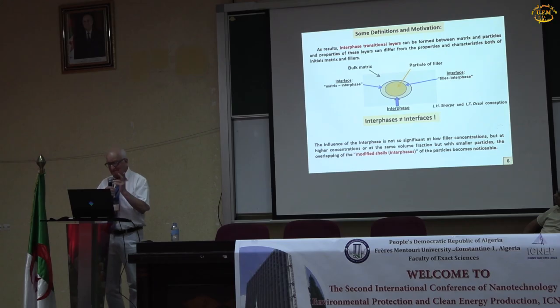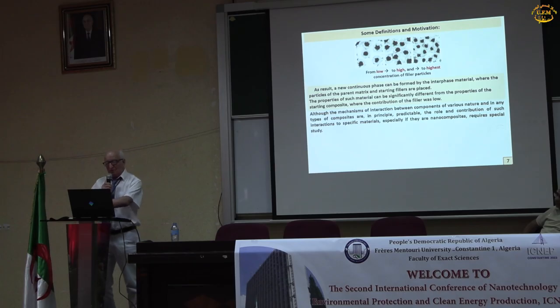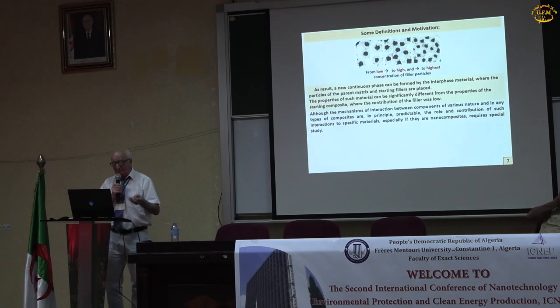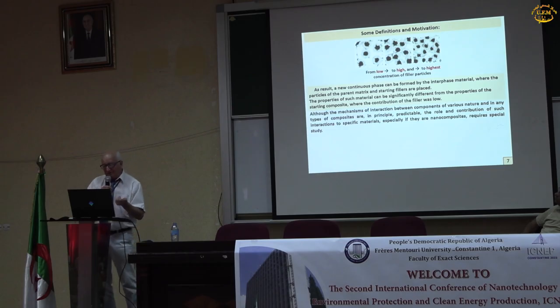It is very important. The influence of the interphase is not so significant at low filler concentration, but at higher concentration, or at the same volume fraction but with smaller particles, the overlapping of the modified shells, the interphases of the particles, becomes noticeable. You see the row from low to the highest concentration of filler particles. As a result, a new continuous phase can be formed by the interphase material, where the particles of the parent matrix and starting fillers are placed. The properties of such materials can be significantly different from the properties of the starting composite, where the contribution of the filler was low.